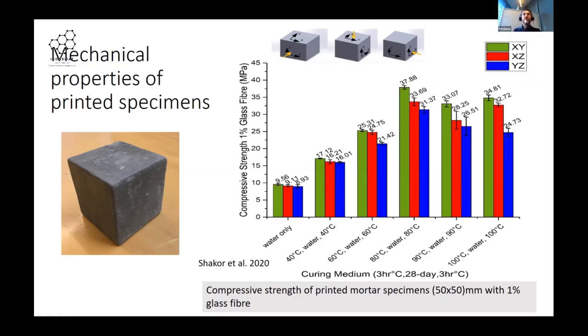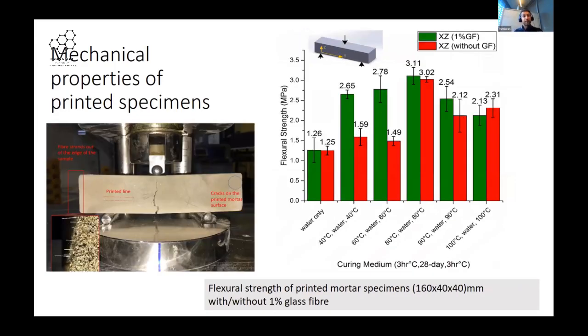So we have three planes we need to test, and we got different results when checking the mechanical properties. However, for the printed specimen in flexural testing, we found that it can be improved as well, but this improvement is not really much compared to the compressive one.